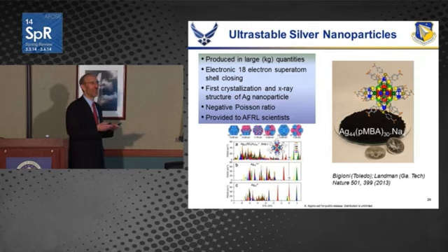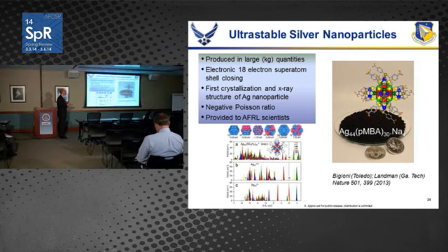And here's an interesting example of some of the unique materials that can emerge as we use these atomically precise clusters as building blocks. So this is work. The synthesis is done by Terry Bigioni at University of Toledo, and the theory, Uzi Landman, who's part of our program. And they've made lattices of, or large amounts of ultrastable silver nanoparticles. So these are the structures. It's got a silver 44 core, and you can bind these together in stable lattices, and the electronic structure tells us why it's stable. It's an 18 electron system.